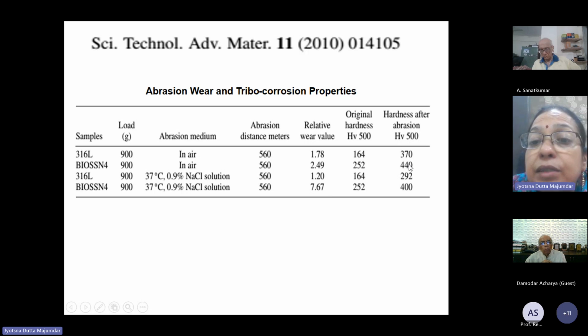Hardness is increased, and hardness after abrasion is also increased, and this relative wear value is significant. This steel is showing a higher value, but this particular 316L, but this bio SSN4 is having more or less a similar value, a little higher value. I do not know, but as hardness is a little higher, it should offer higher abrasion wear as well as tribocorrosion performance, but it's not showing so. Hardness, if you say, after abrasion it is increased, but the abrasive wear value is not really. So these are research results.